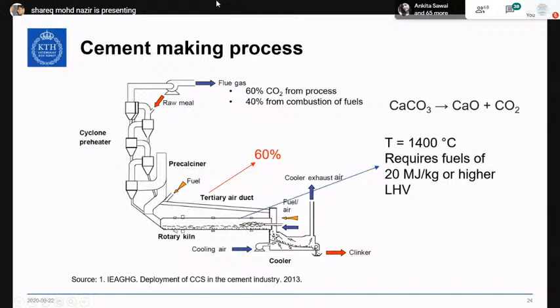The temperature that is required in the rotary kiln is around 1,400 degrees centigrade for this reaction to happen, and it requires fuels of 20 megajoule per kg or higher LHV. So we are speaking about coal or methane. People are testing hydrogen here these days, but we are speaking about coal and methane basically, and the majority of the clinkers use coal these days, and they are trying to have a mix of bio-based fuels and coal here.